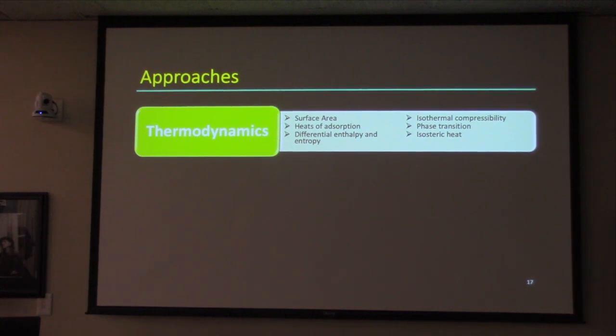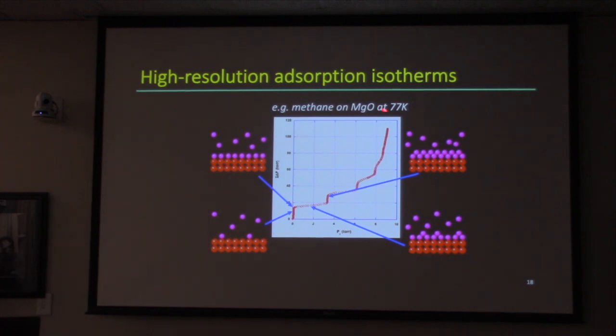I also was intrigued by the transition from 2 to 3 dimensions. How is it that things at the interface change in their thermodynamic properties to what they're like when they're a bulk hunk of methane or a bulk hunk of nitrogen and argon? And so a lot of this is I needed a way to study that. And here's a simple example. We're really lucky because methane absorbs on magnesium oxide in a layer by layer like fashion. And in fact, I looked back through some of the old notebooks. We actually can identify 6 and 7 layering transitions. And those are typically talked about as being wetting systems, systems that grow layer by layer like at the interface.